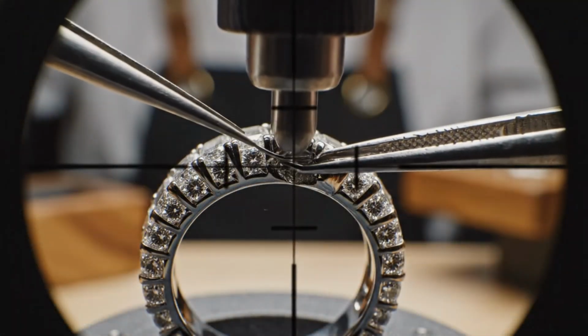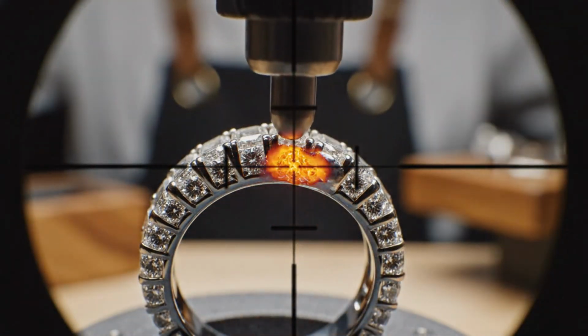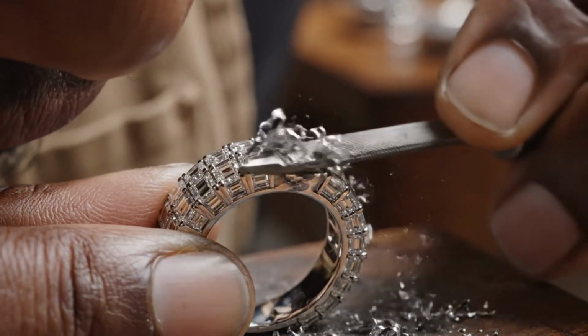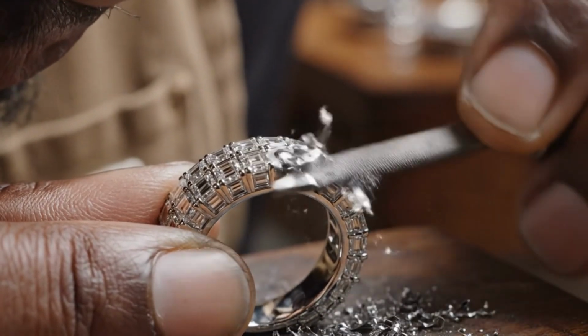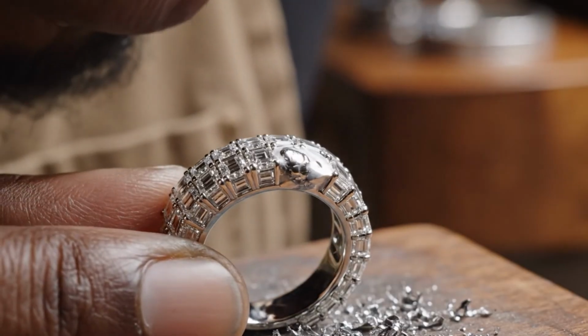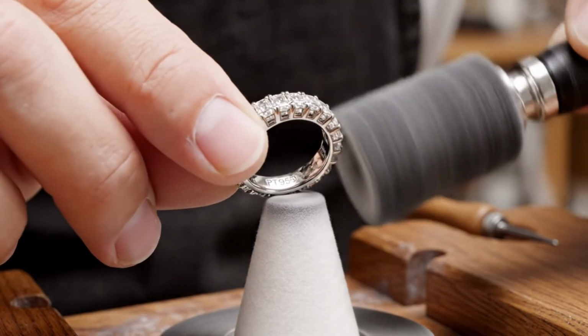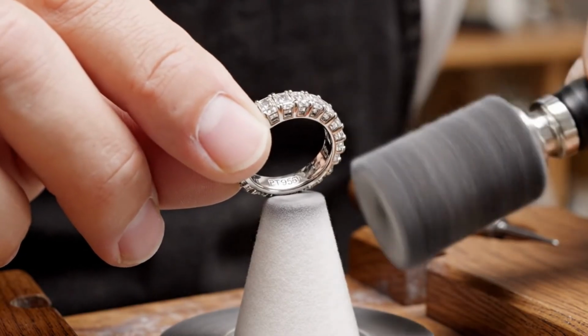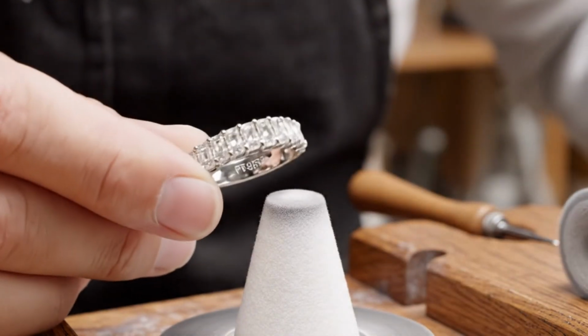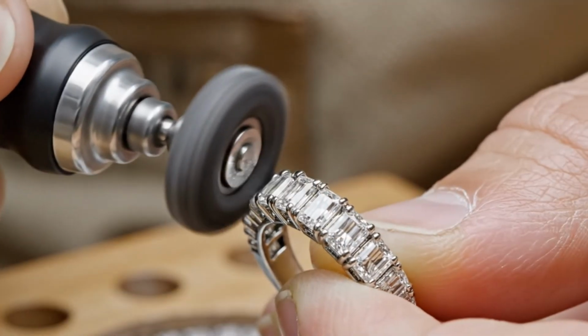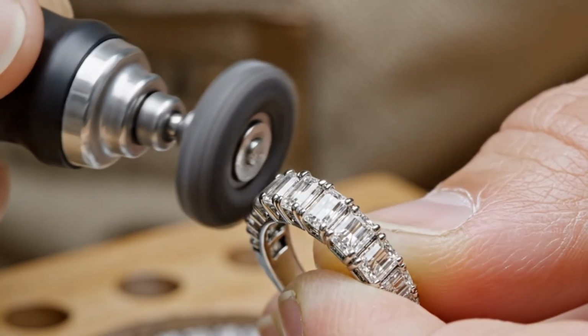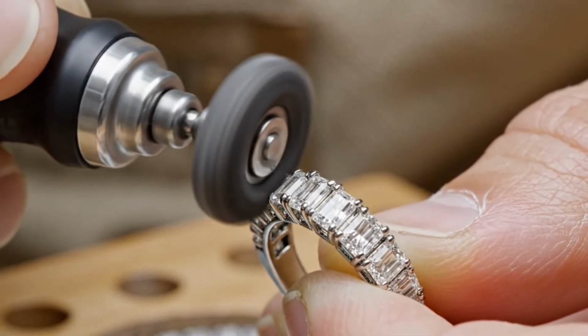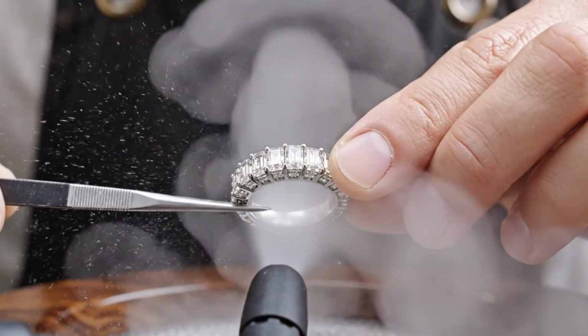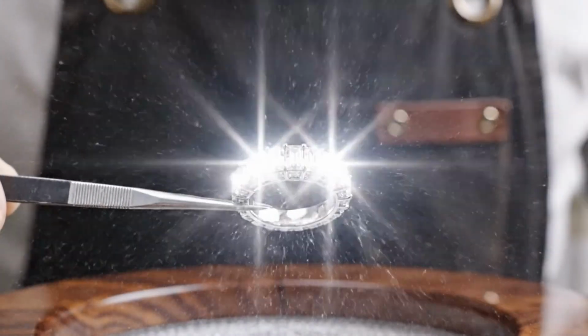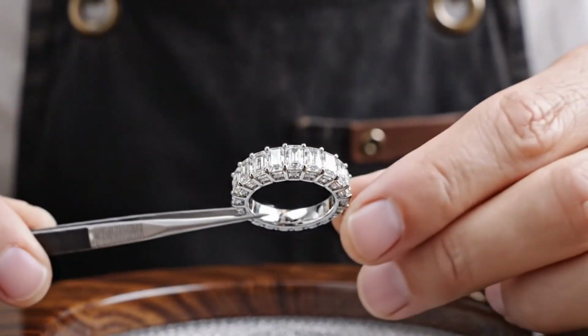We take the ring to the laser welder to fill a deep gouge on the side, melting fresh platinum into the void. The file smooths the new weld flush with the surface, erasing the damage completely and restoring the structural integrity of the heavy band. A light polish is applied to the interior, preserving the engraving while removing the dullness that accumulates from contact with the skin. We avoid over-polishing the prongs, as removing too much metal every year would eventually weaken the setting and compromise the stone's security. The steam jet blasts through the gallery one last time, ensuring the diamonds return to their original blinding capacity of light performance.